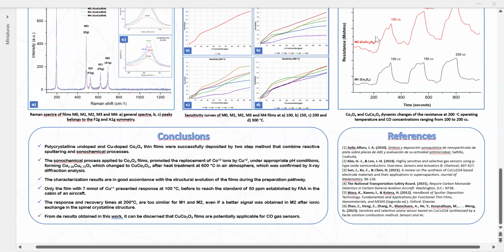Only the film with 7 millimoles of copper ions presented a response at 100 Celsius before reaching the standard of 50 ppm established by the Federal Aviation Administration for the cabin of an aircraft. The response and recovery times at 200 Celsius are very similar for M2 and M1, even if a better signal was obtained in M2 after ionic exchange in the spinel crystalline structure.